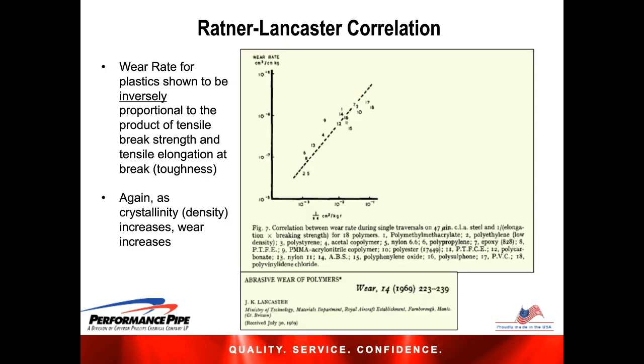In this slide here, we show some data from an article by Lancaster, which was published in the Wear magazine in 1969, so it's a fairly dated article, but the science has actually remained much the same. This plot basically shows the wear rate as an inverse of the ultimate break strength and the elongation product, which is shown on the x-axis here. And plots like this have been subsequently shown in the literature many times and are referred to as the Ratner-Lancaster Correlation.